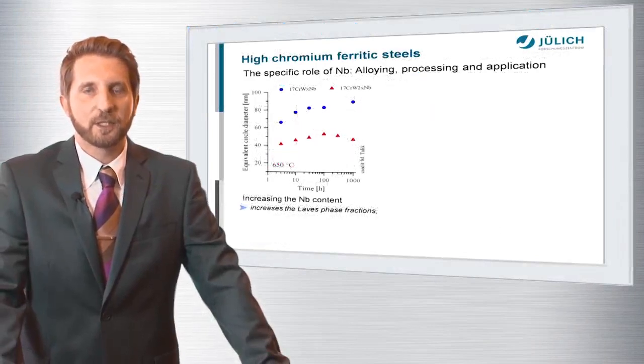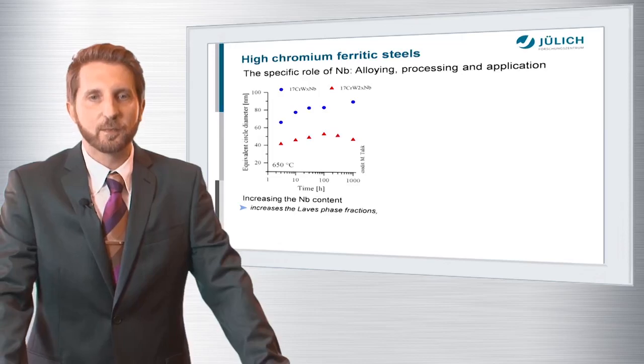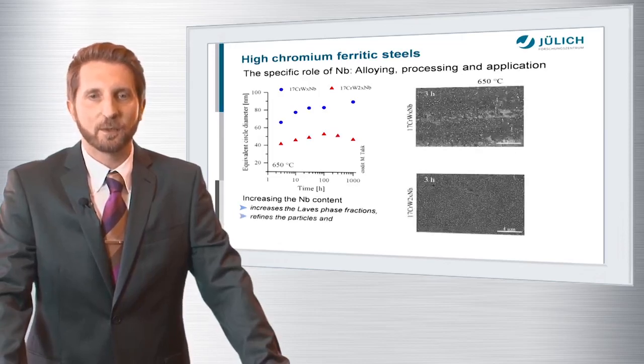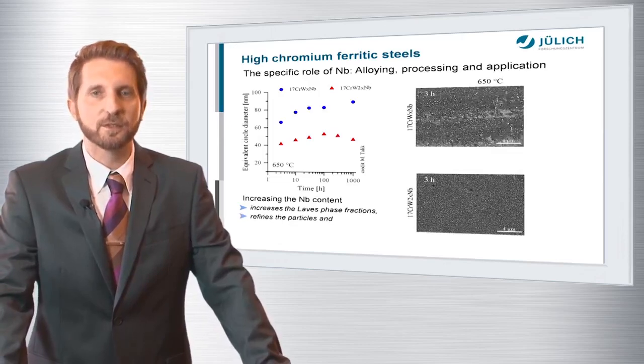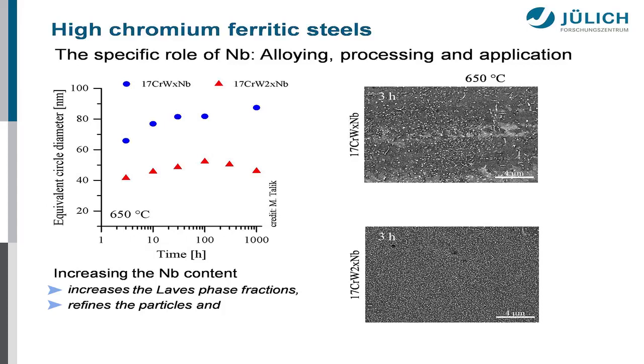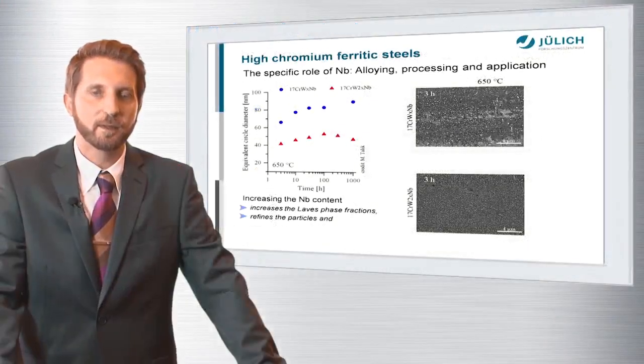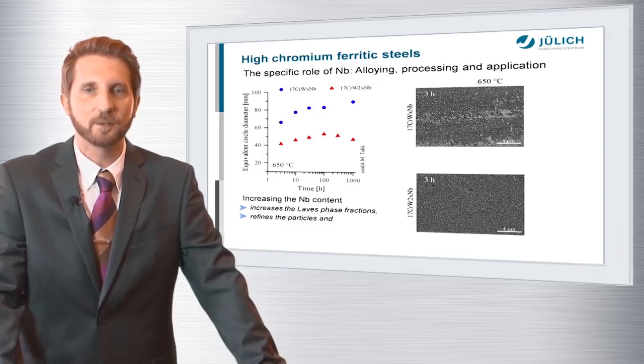So if we now change, or let's say in this case, increase the niobium content, it raises the volume fraction of the Laves phase. This is shown in these 2 micrographs. So these are micrographs taken from 650 degrees C annealing after 3 hours. The upper picture is from one of our new trial alloys with 17% chromium, a specific tungsten content and a single niobium content. The lower picture is from an alloy which is quite similar considering the chromium content and the tungsten content. The only difference is that the niobium content is doubled.